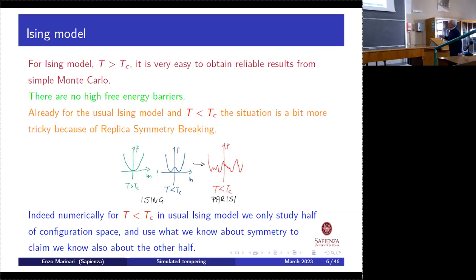Because you see, so look at that. Don't look at this one. This is Parisi. It's complicated. We look at it in the next slide. But so this is typically free energy versus magnetization. Okay, high temperature is just a parabolic behavior close to m equals 0, and clearly doing Monte Carlo is pretty easy. But as soon as you go in the broken phase, already you get a phase transition. Right? What does it mean, a phase transition? It means that you have two possible stable states of the system, right? And that this barrier is an infinite barrier.